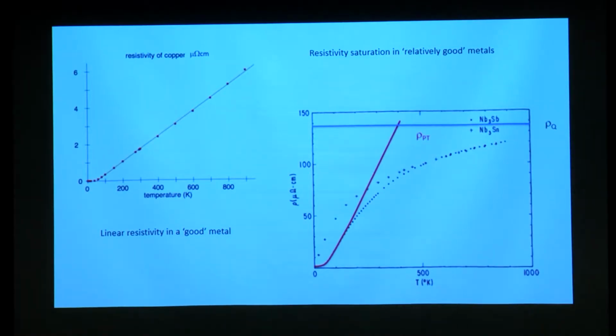Copper is something which we all know, and here I show the electrical resistivity of copper as a function of temperature. In this field, it is important to know numbers and perhaps even respect them. Here you see the resistivity is rather small, a few micro-ohm centimeter, 2, 4, 6, and so on. Copper is a very good metal, so its electrical resistivity is very small. But it is not linear at very low temperatures. As a matter of fact, there is a very famous result due to Bloch and Gruneisen, which says that for very pure metals, it should go as the fifth power of the absolute temperature. But you see that for most of the temperatures accessible to us, it is linear.